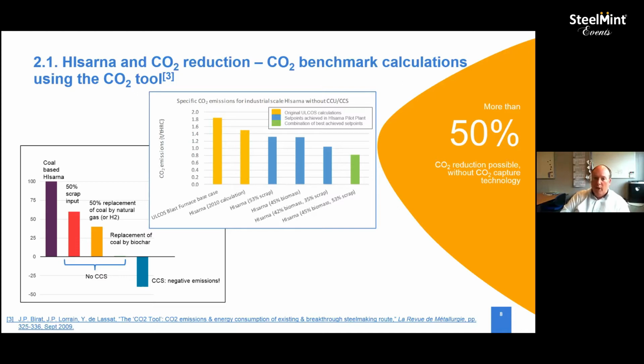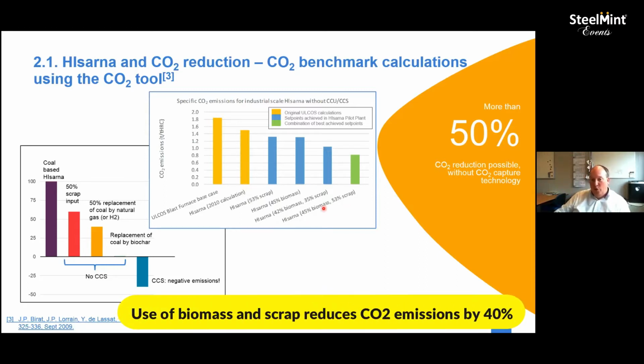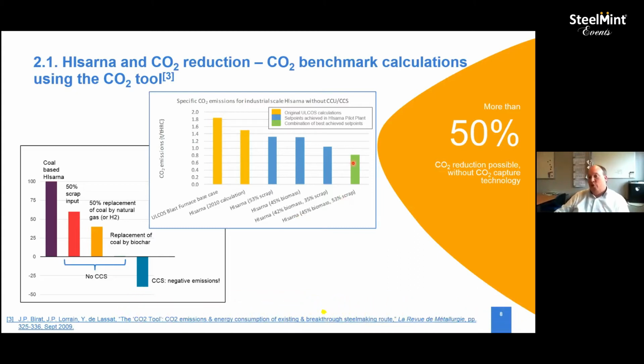And using that model and the pilot plant results, we could demonstrate that if you use scrap or biomass, you already reduce the CO2 footprint significantly compared to the standard blast furnace, and also to the original HIsarna calculation that was done with the model. And if you combine the biomass and the scrap in the best combination that we'd achieved, you go to about 40% reduction in CO2 emissions. If you take the two best points we achieved on biomass and scrap, you even halve the CO2 emissions across the route. And that is without carbon capture. That is purely by emitting less CO2, but assuming that the biomass you use is a truly sustainable biomass.